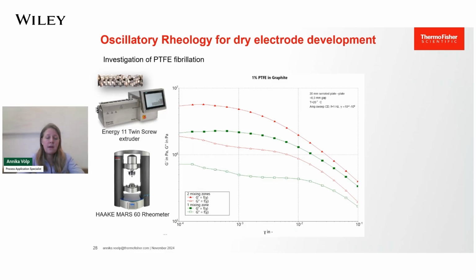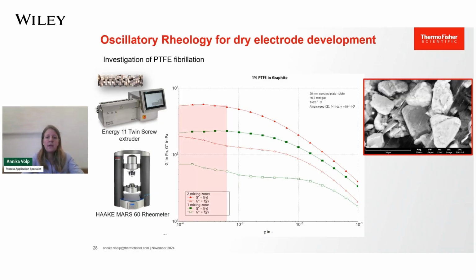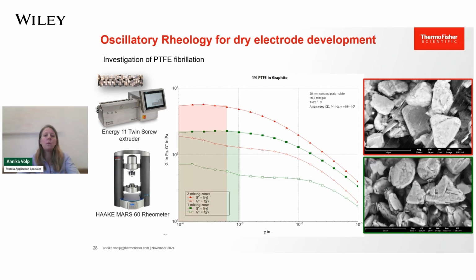This is another sample, an amplitude sweep test on a PTFE graphite mixture that was mixed with a twin screw extruder and passed through 1 or 2 mixing zones in the extruder respectively. PTFE is known to form fibrils under shear and acting as a binder in dry processed electrodes. The sample that was exposed to 2 mixing zones in the extruder exhibits a higher plateau value of G prime in the linear viscoelastic regime than the sample exposed to only 1 mixing zone.